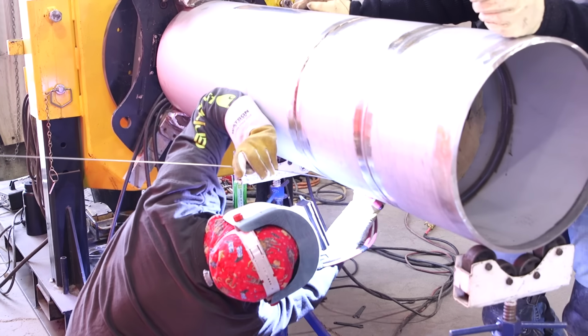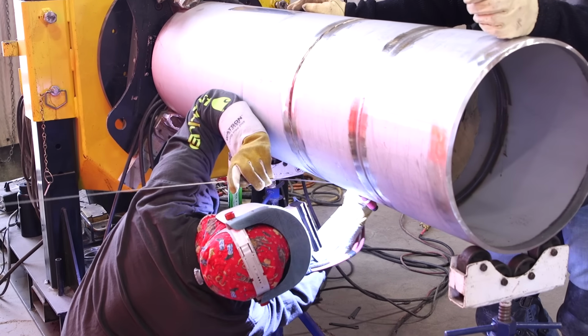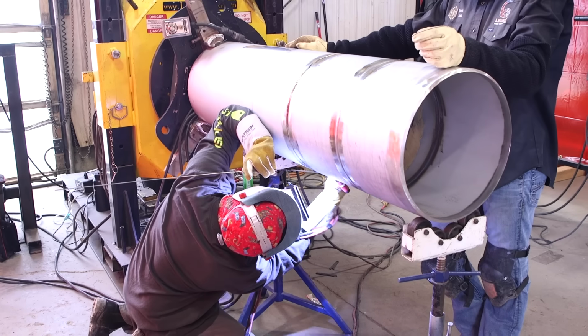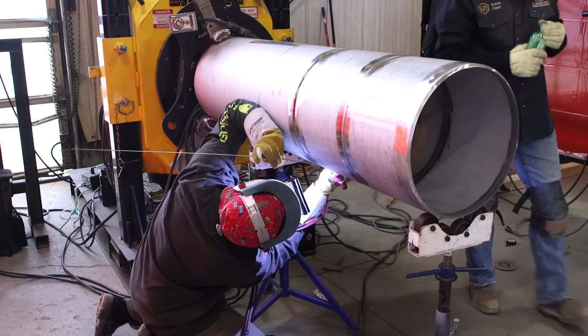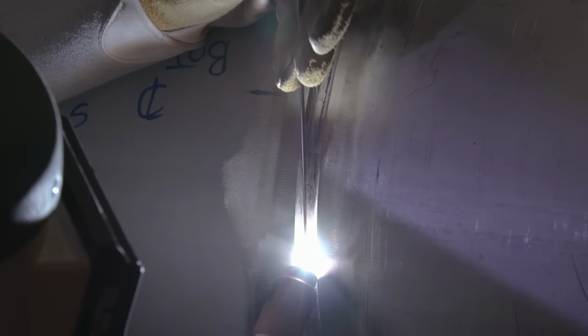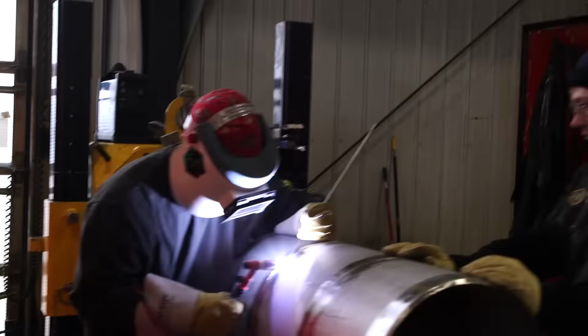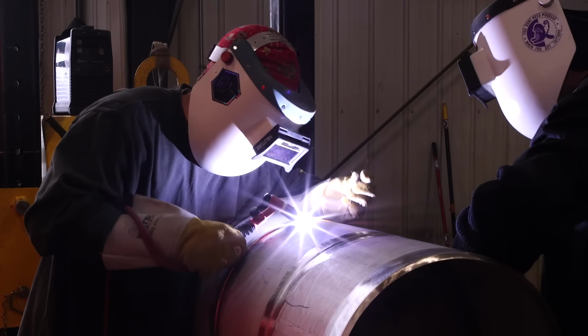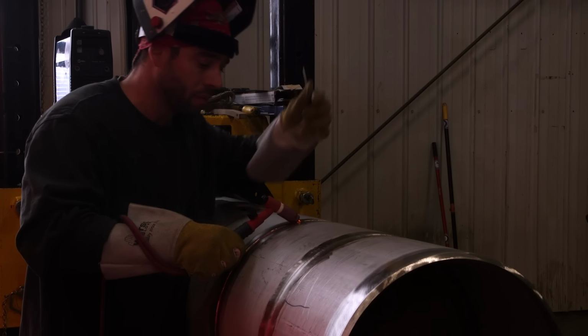Basically, as I weld, there are certain spots where I do need to increase the welding current. The bottom usually will seem kind of cold at the start. And when you start welding, usually about 4 o'clock, it starts being at a normal welding temperature. I'm going in the uphill position and I'm using my filler metal as somewhat of a heat sink. It is a solid mass and there's only so much energy it's going to take to keep the weld puddle in its liquid state. So in turn you can manipulate the rate of solidification and liquefaction of the welding puddle that way.